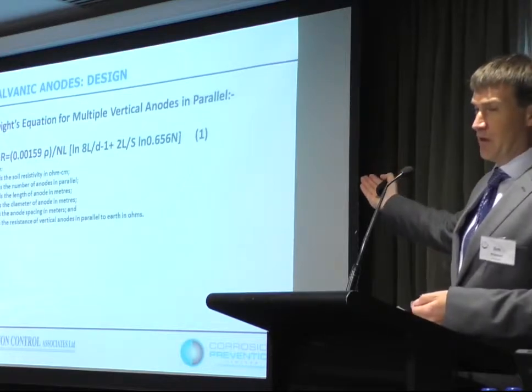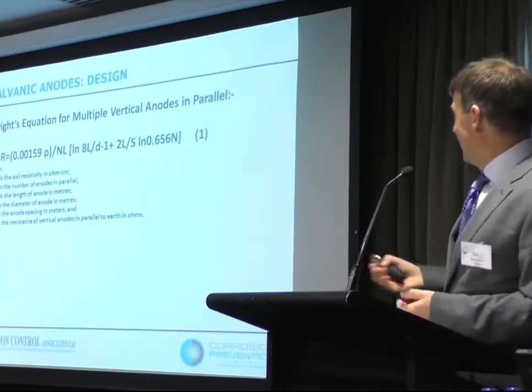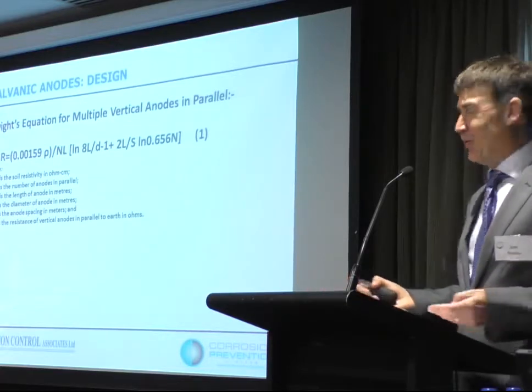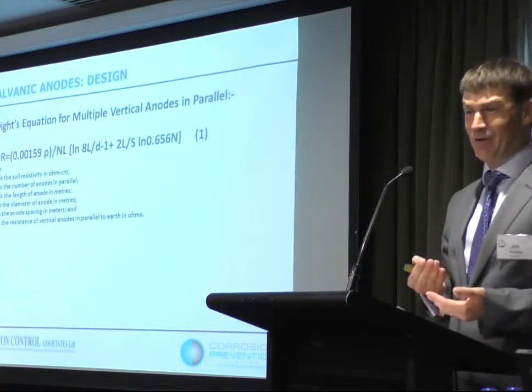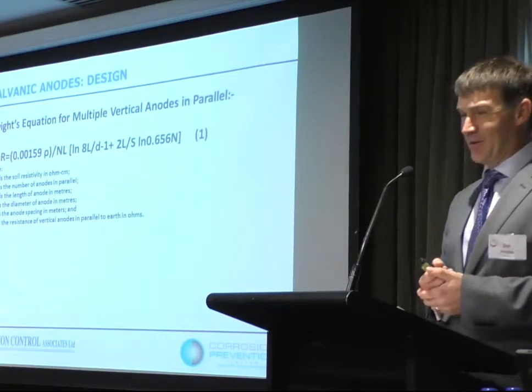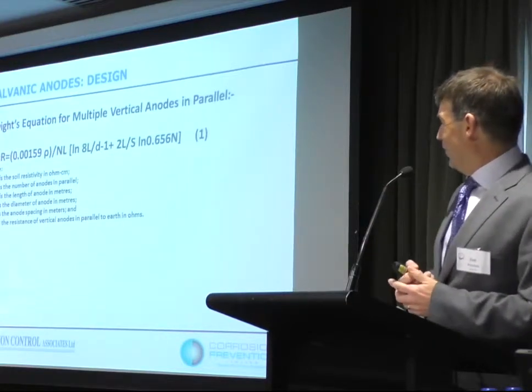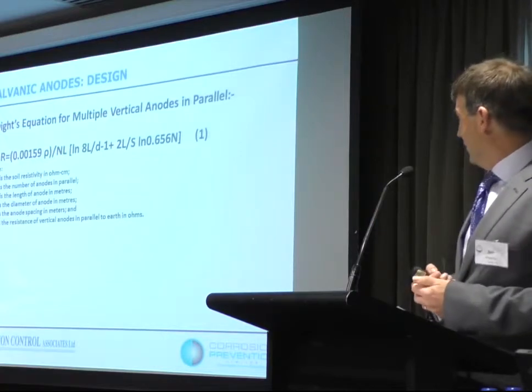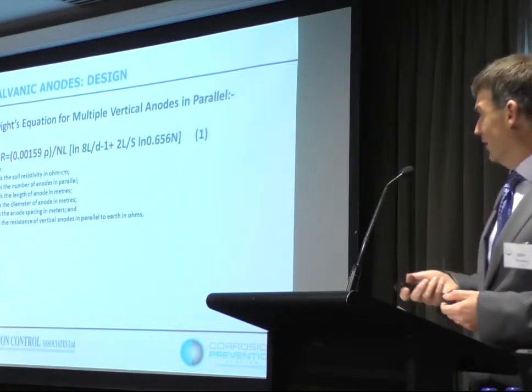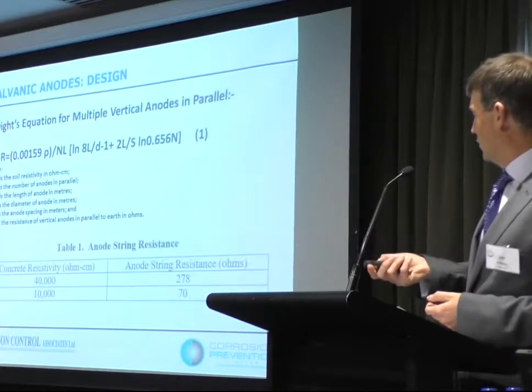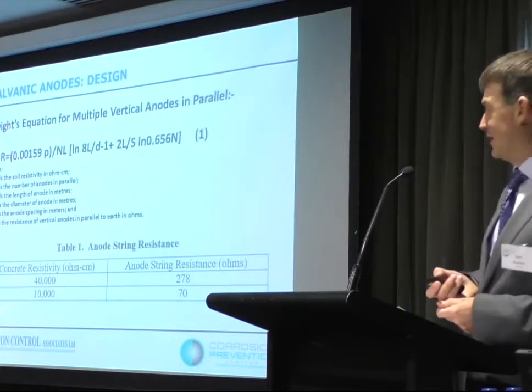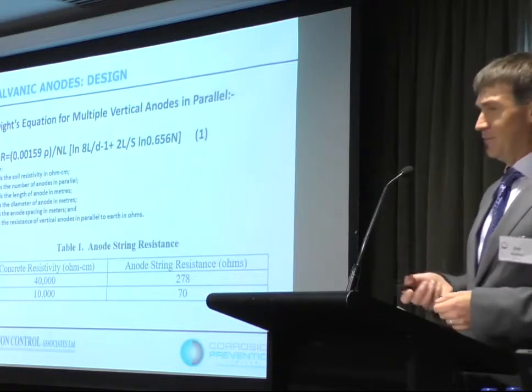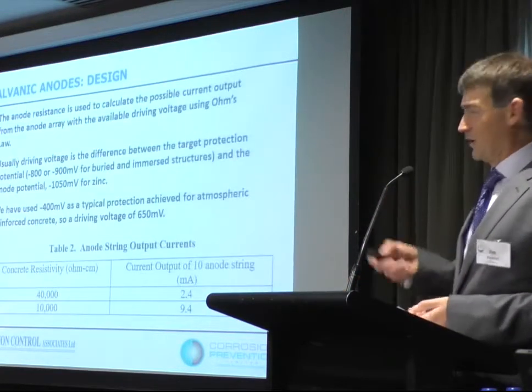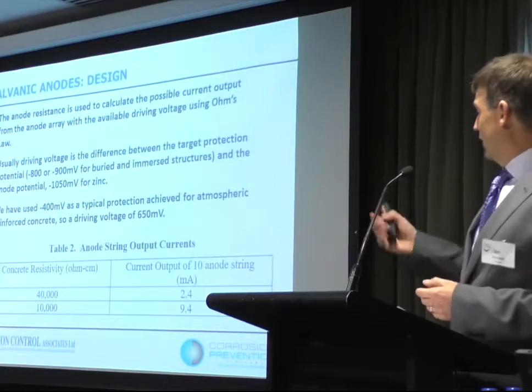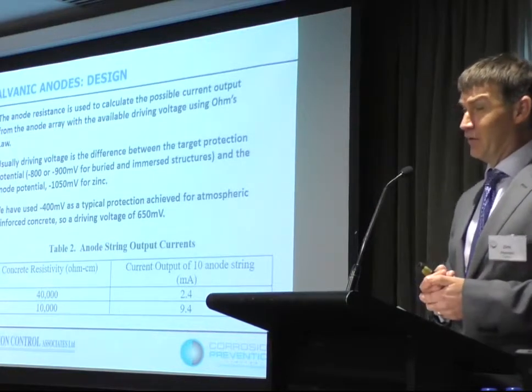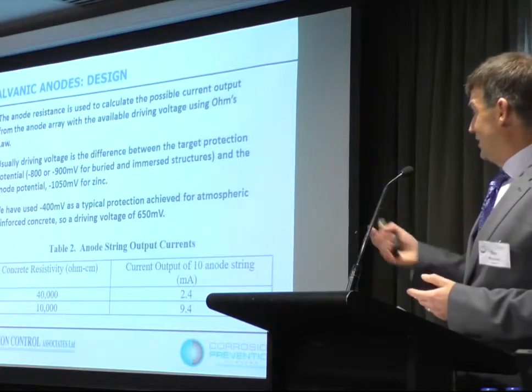So we started off with one of Dwight's equations. There's a whole raft of Dwight's equations. They're not perfect. And in this example, we're using a very shallow anode. It's not a true resistance to earth or remote earth. But all of that's going to work in the favor of this calculation, really. So we plug all our numbers into this equation, and we get a resistance for our two different resistivities, 278 and 70. What we do with that resistance is we take a much simpler equation, Ohm's law, and we can work out the current output for each of those strings of anode at the two different resistivities.